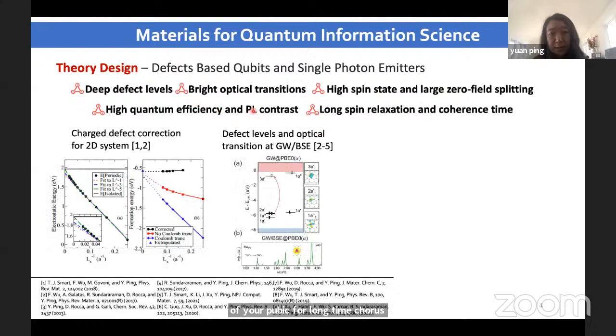Correspondingly, we have been computing these properties, developing methods for 2D materials. The reason we investigated defects as qubits in 2D materials is motivated by quite a few experimental works for hBN. First, we developed methods to deal with the charge defect correction. This is because for the charge defect in 2D material, the convergence is problematic. And in this work, we developed the methods where we do not need any supercell extrapolation to converge the calculation.